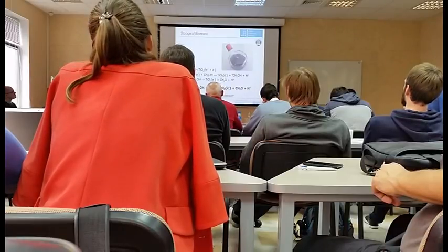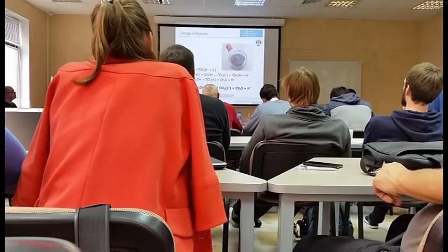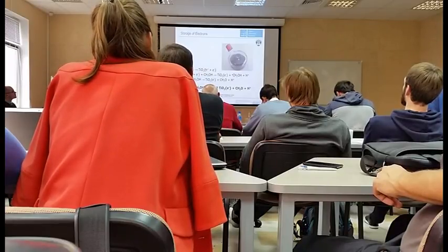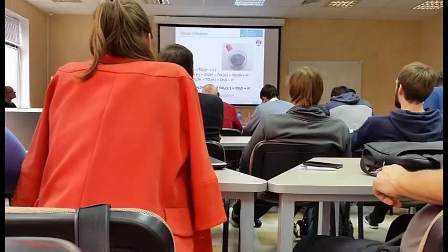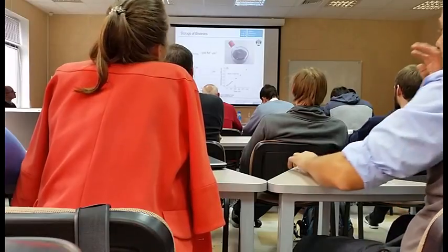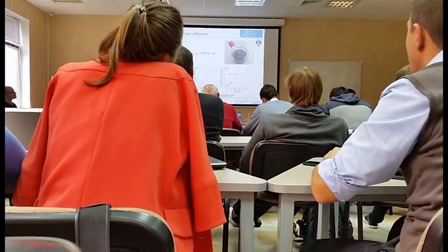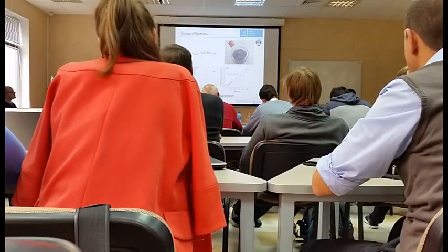You don't have oxygen, so you cannot reduce oxygen, so the electrons form this blue color, which is just the trapped electrons on the titanium sites in the form of titanium 3+ ions. This goes linearly with illumination. This is the strong blue color that you're forming here, an extremely broad absorption spectrum.